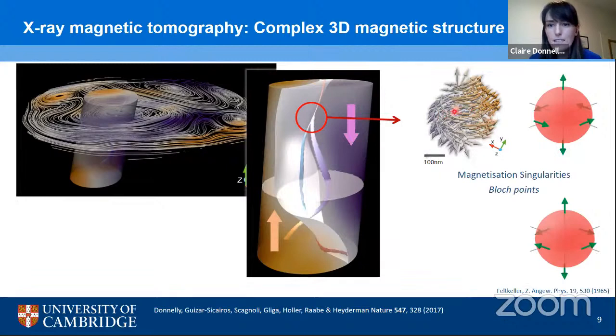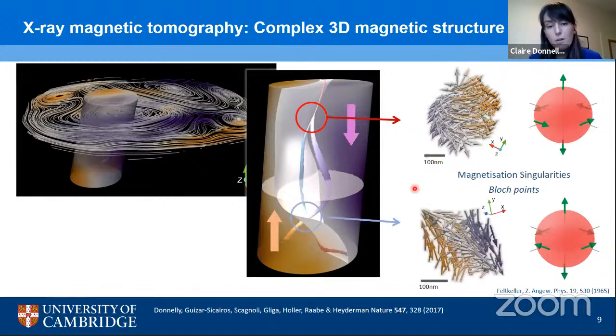We see a circulating Bloch point at the top crossing point, with the magnetization circulating in the plane, and pointing up and down, above and below. And at the other point, we have a more twisted state, which we believe is an anti-Bloch point. So just as we have a vortex and an anti-vortex, here we have a Bloch point and an anti-Bloch point, which we believe are likely to have formed as a pair within the bulk of our structure.